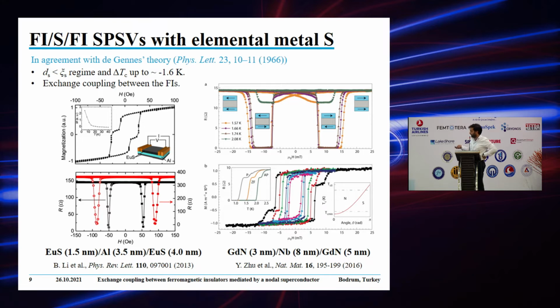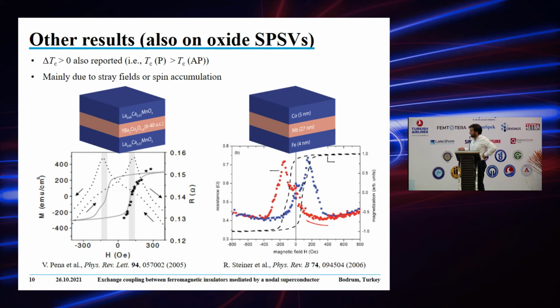As I explained before, there was also other work where they reported delta Tc larger than 0, so Tc parallel larger than antiparallel. But most of this work was done also on oxide materials. This was the group of Santamaria, Jacobo, in Spain, and in this case the variations are small, but mostly related to stray fields, or, for other metallic systems, the same thing was also seen, but related to spin accumulation.